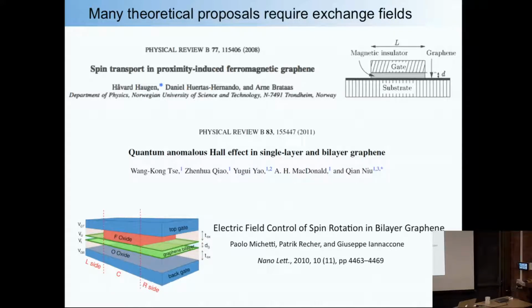So later on in the talk, I will mention hydrogen atoms creating magnetic moments, and the exchange field is pretty large, larger than expected. And Jaroslav Fabian developed a theory. He says, how can it be so large? It is because the wave function must be localizing to make it large. So he's proposed this idea of resonant enhancement of exchange coupling. If it was completely delocalized, it would be small, like in the hyperfine coupling. You want them to be more localized. So that could play a role in all that.